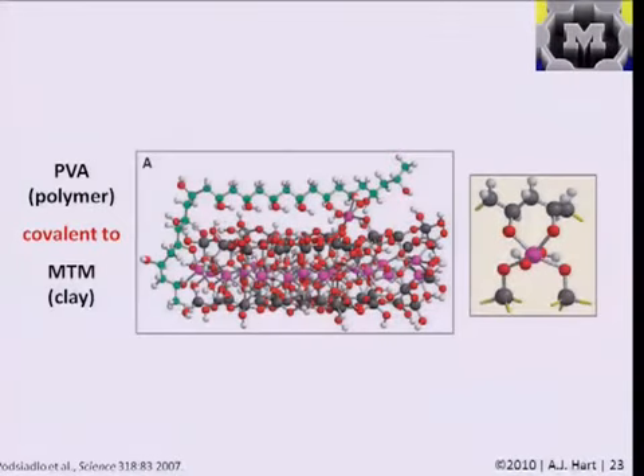And their study also contains some analysis of the interactions between the polymer, PVA, and the MTM, the clay, or the organic component and the inorganic component. They found that indeed under the conditions that they used, the material was so strong because there was actually covalent bonding between the polymer and the clay, and this was related to an aluminum atom that was on the surface of the clay and associated itself with the polymer. So it was indeed this engineering of the molecular interaction that made this material have the properties that were found.